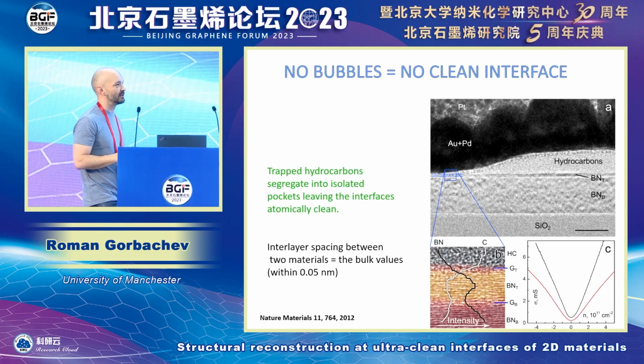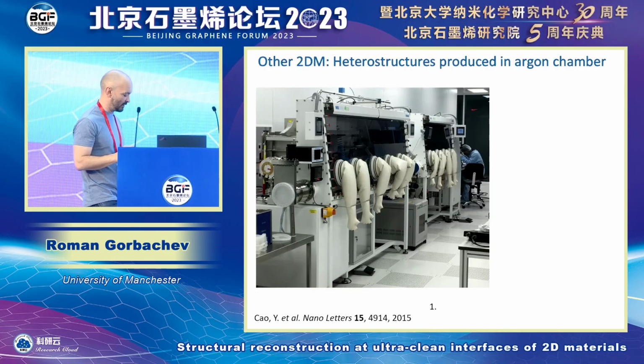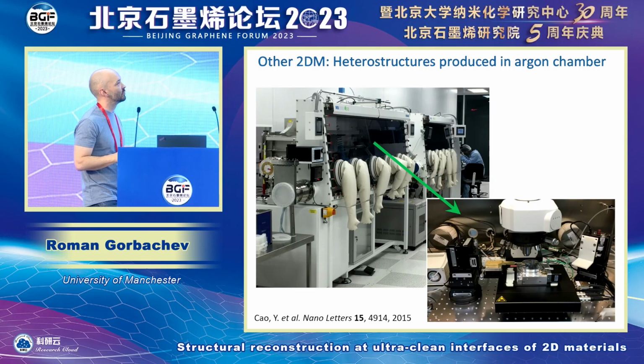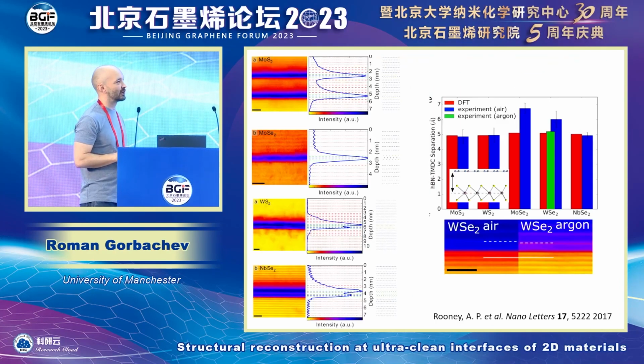However, later we found out that these pockets, they are basically full of hydrocarbons, which are organic molecules that are floating in the air all the time. They are produced by us, by polymers, by plastics, by cars, and all of that is being trapped between the layers. So the next stage in technology was trying to put this in a very clean argon chamber. It is, in terms of vacuum, not very clean. It's about 10 to the minus 4 millibar partial pressure of water and oxygen. So compared to UHV it's not very good, but it gave us a lot of space to explore, especially those materials that are air sensitive.